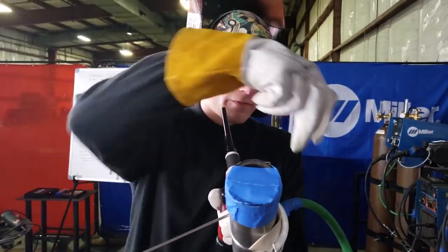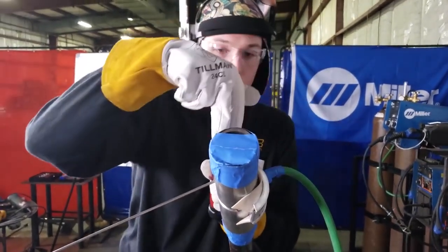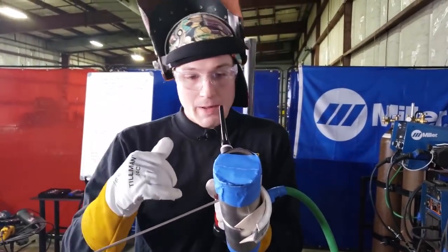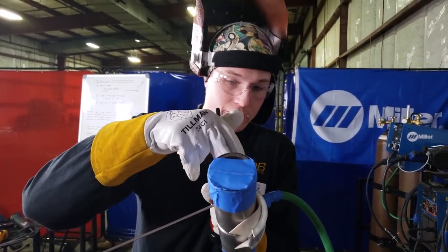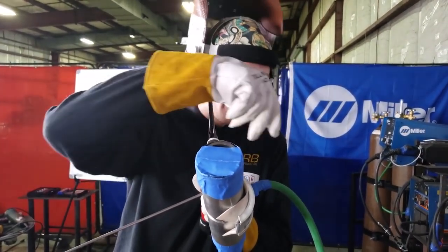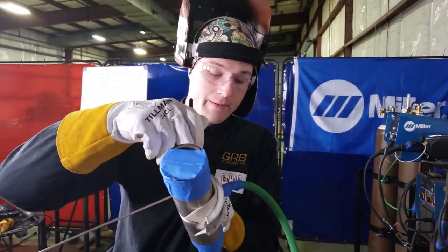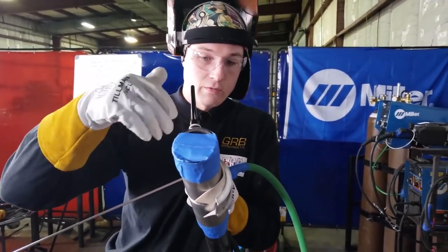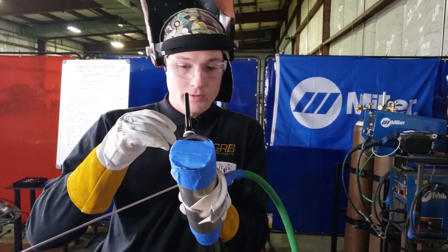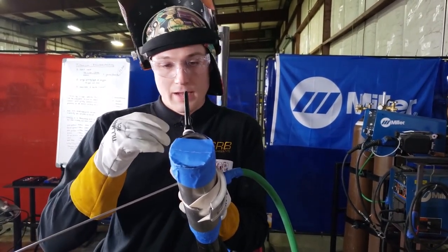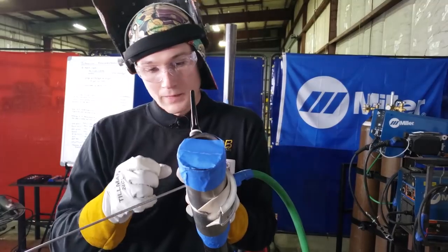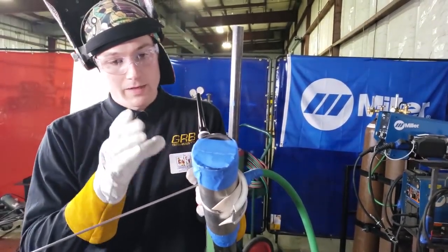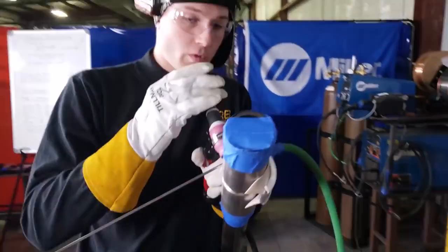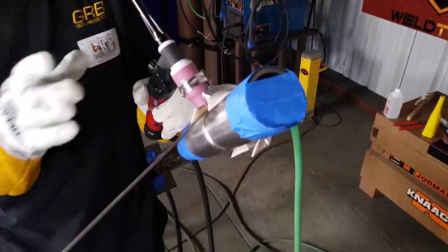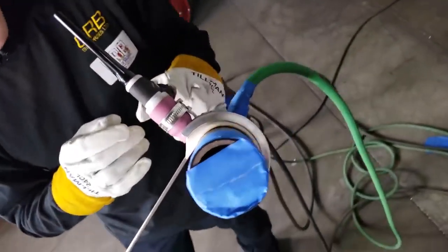Basically all the deposited metal from the travel distance from 3 o'clock up to 12 o'clock is protected away from the atmosphere using this Huntingdon Fusion trailing shield here. And the argon from the bottle that feeds the argon to the trailing shield is less than 25 parts per million, so the weld zone and the heat affected zone will be less than 25 parts per million, so it will come out silver. Everything from the torch to the trailing shield is protecting any and all deposited metal away from the atmosphere, so it does not oxidize and form oxides.